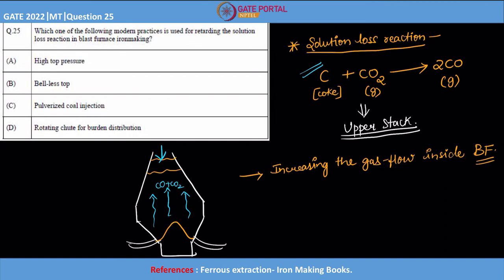For that to happen, what one has to do is to form some kind of obstacle for this escaping gas. How can we do it? By various mechanisms. But the main motto is to provide some top pressure. This is called high top pressure. If you actually maintain this high top pressure...